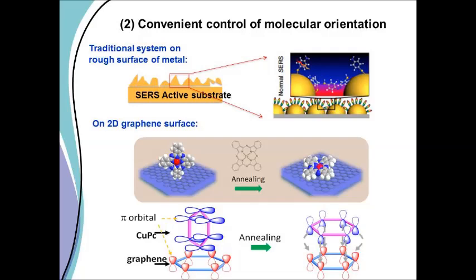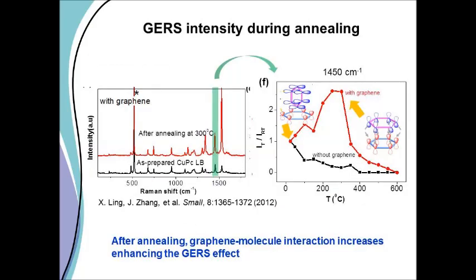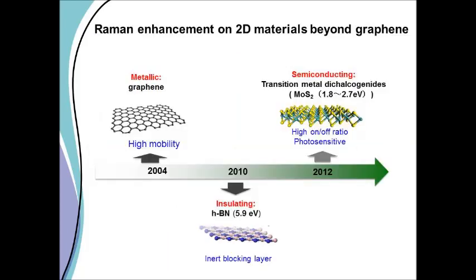And it has a polarization because with annealing, we can make the molecules stand up if they're asymmetric and line up the pi bonds, and that gives it further enhancement. So we could see that effect, and that's shown here, the effect of annealing. We get more of this GERS effect than without it. And this is the last part of this. So if you have one layered compound that gives an enhancement effect, are there other layered compounds that give us an enhancement?